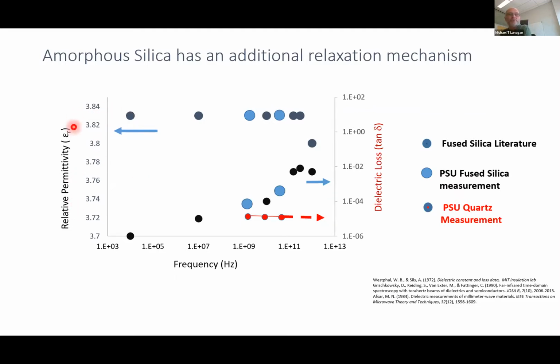Here we're looking at the permittivity and loss as a function of frequency, and it's pretty flat in terms of the permittivity, and we start to see a roll-off as we get into the terahertz range. Correspondingly, we're starting to see, even at lower frequencies in the 5G range, this tail coming up for the glass, and then we think we see a peak here. This is where some more research will need to happen to make sure we understand where this peak occurs for the fused silica. But what's really interesting, quartz doesn't have this.